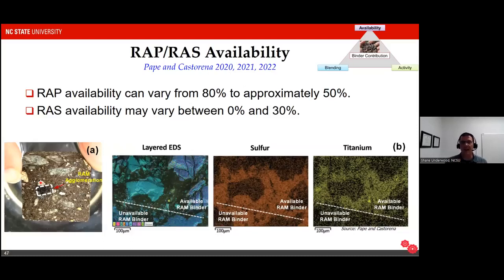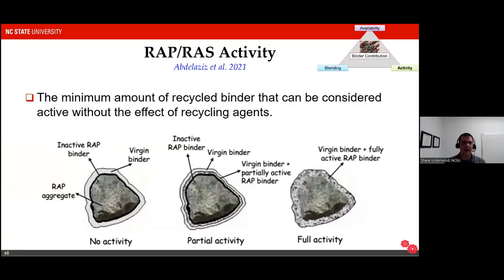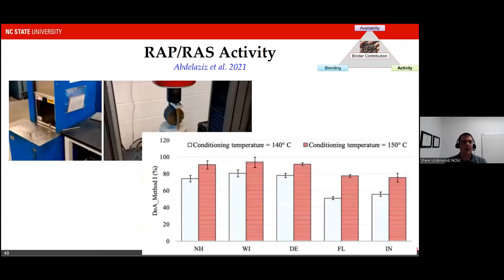In addition to getting binder available, that binder has to become active. And this is an area that has been studied extensively by groups in Texas, as well as at University of Parma in Italy. And here they've been trying to figure out that just because the binder is available doesn't mean it actually activates. You might not get enough heat transfer to make the binder blend in the mixture. And in their case, they've developed a method to use indirect tension testing to try and understand how much binder will become available. And they've been able to show that binder availability increases with temperature. So practical application, if the material is processed at a higher temperature, you're more likely to get activity, and therefore that's going to improve the availability and the activity of the binder in the mixture, and you're going to get better blending. And if you get better blending, then you get better performance at the end of the day.